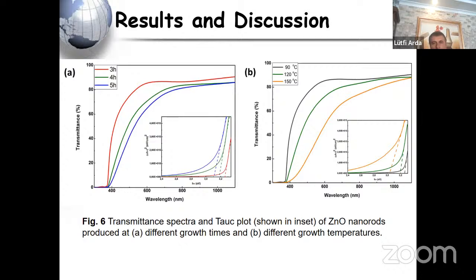In our study, the optical transmittance value depends on the nanorods' diameter and length. I show you in table 2. Also, the band gap and the transmission I showed you in the previous table, table 3. The average optical transmittance and the band gap value decrease as the diameters and lengths of nanorods increase. Consequently, the volume of nanorods increases,